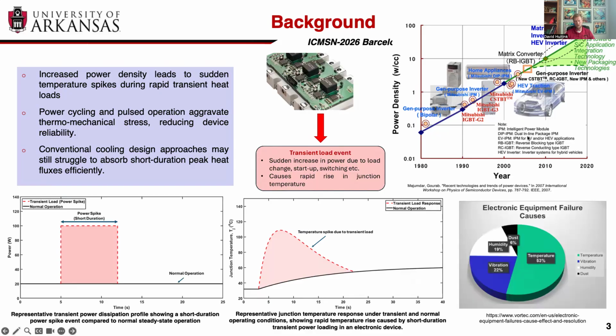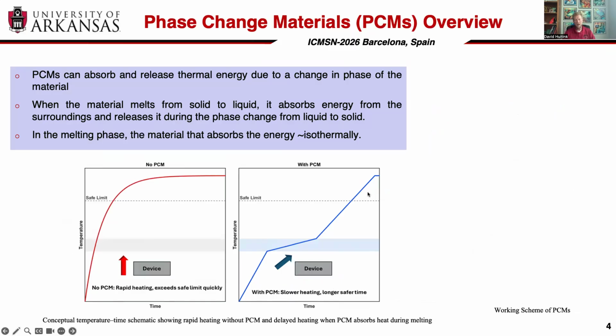to electronic failure. Temperature and temperature cycling are the two dominant reasons for reliability failure in electronics, because of the things that happen with material degradation as well as thermomechanically induced fatigue events in electronics. And so being able to control these transient temperature spikes is a very important aspect of the overall thermal management solution. And this is where PCMs or phase change materials have specific opportunity.